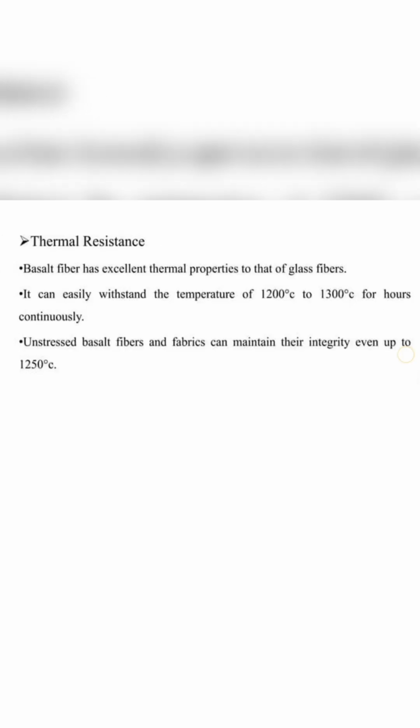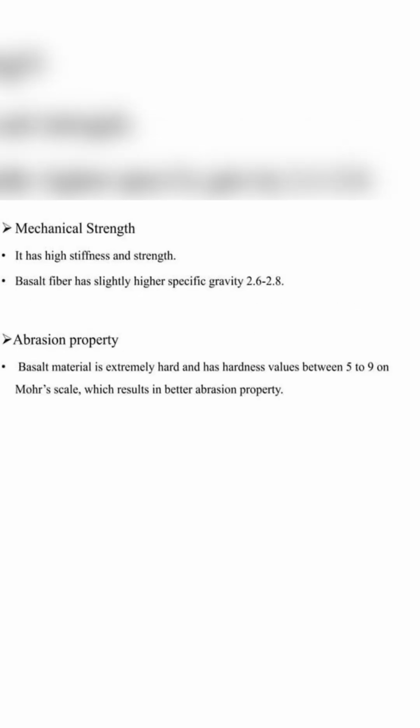And the thermal resistance of basalt fiber. It can easily withstand the temperature up to 1200 or 1300 for a few hours continuously. The unstressed basalt fibers and fabrics can maintain their integrity even up to 1250 degrees Celsius.